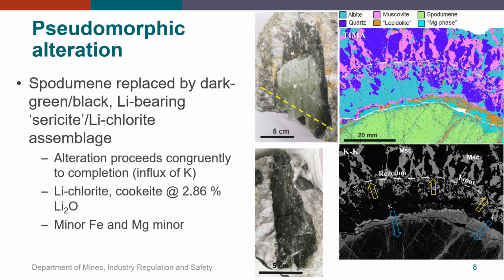About the crystal margin, the alteration was mapped as a mixture of secondary lepidolite and a magnesium phase. However, the mineralogy was confirmed by XRD analysis as consisting of a mixture of mica as secondary muscovite and a lithium-chlorite phase, cookeite. You can see the fine-scale nature of alteration as veins penetrate the crystal interior. This is shown more clearly in the potassium distribution map below the mineral map. This type of alteration progresses congruently inwards until the spodumene is completely replaced in situ. As you can see, an example here where that has happened with this large spodumene crystal being completely replaced.